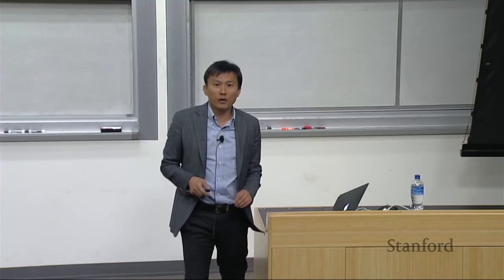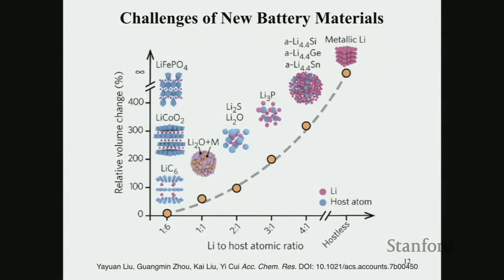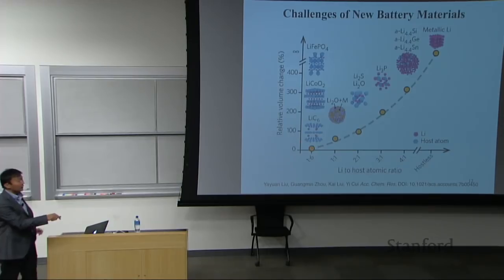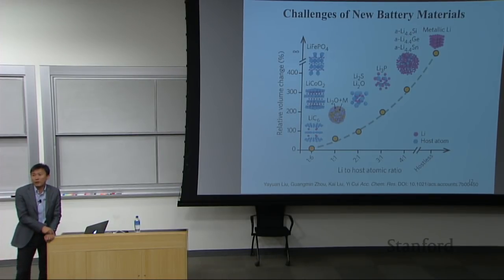So the reason is the following. This is a slide I asked my student Ya Yuan to make. This is the relative volume change. I plotted it as lithium versus the host atom. You notice that the material used in current technology is 1 lithium to 6 carbon, so the lithium to carbon ratio is 1 to 6. Lithium cobalt oxide roughly uses half of the lithium. Lithium iron phosphate is also about 1 to 6. The volume change right here is about 10% or less, very small.